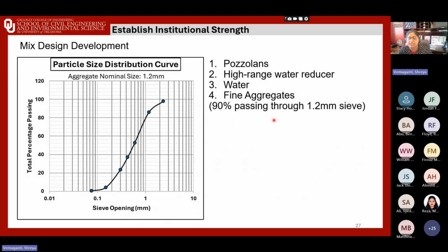And we are still working through this. So you'll have more and more reports to be able to see that information if you're interested, or I'm absolutely happy to share that information and what we have here. We have to tailor those admixture dosages for flowability, durability and buildability. So we ensured that 90% passing of fine aggregates through a 1.2 millimeter sieve was used.